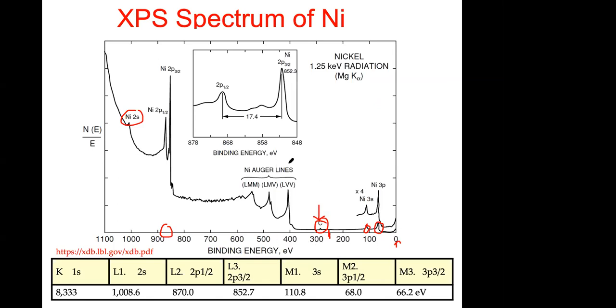Anyway, the other thing that you see is that you can see the Auger lines, and that's basically for this magnesium K-alpha. I told you that if you use an aluminum K-alpha source, and you do the spectra and plot it against binding energy, all these peaks are going to appear at the binding energy that they are known to be according to this table, but the Auger line is going to move, because the Auger line doesn't depend on the energy of the source. It depends on the transition, internal transition.